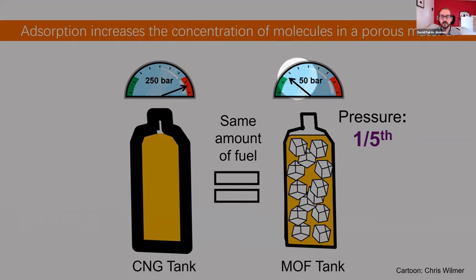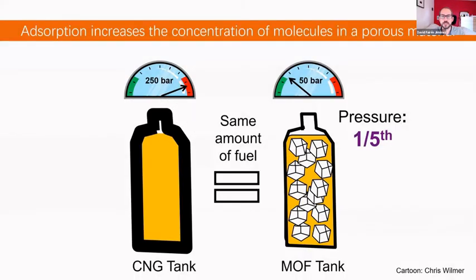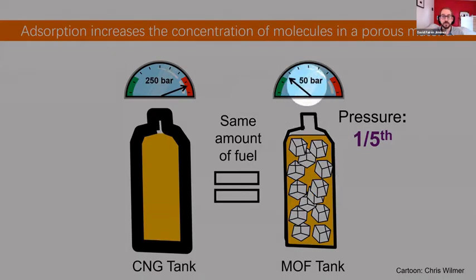filled with porous materials, you just need to have a fraction of the original pressure, okay? You can really go up to 50 bar, and that's going to be exactly the same amount of fuel. So this is going to be lighter because you can see also of this cylinder, that's going to be thinner than this one, okay? Just because this tank needs to resist this extremely high pressure, okay? It's going to be safer as well, just being able to have less pressure. This is for natural gas.